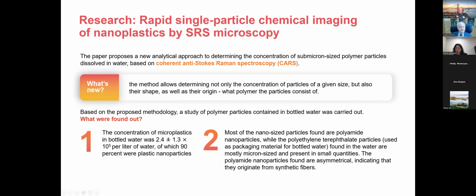And it is based on coherent anti-Stokes Raman spectroscopy. What is new? This method allows determining not only the concentration of particles of a given size, but also their shape as well as their origin, what polymer the particles consist of. And it goes from the micron range down to the nanometer range. And of course, when you go from the higher sizes to smaller sizes, it's clear that the number of particles discovered was immense, 2.4 multiplied by 10 to the 5 particles per liter of water.